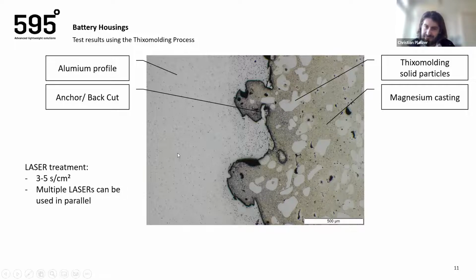To give you a better understanding, the left one that you see here is the aluminum profile, and the right one is the Thixo-molded magnesium. You can see also the solid particles that you will always see in a Thixo-molded product, because we are not melting up the magnesium completely. We are working in the semi-solid region of the alloy, and the advantage of the Thixo-molding is also contributing to this bonding technology, because the shrinkage of the magnesium alloy is much lower than in die casting when you are overmolding with overheated magnesium. So it's easier for the magnesium to stay in those laser structures without getting pulled out during the cooling to room temperature.